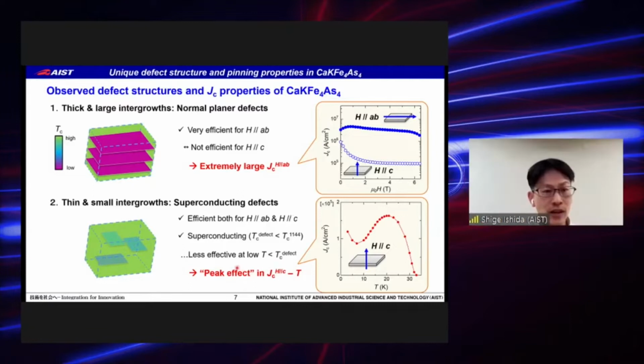So this small thin intergrowth is superconducting at low temperatures. Maybe the defects become less effective as pinning centers. So we expect these kinds of defects are responsible for the peak effect, the increase in JC with increasing temperature observed in this calcium potassium 1144 material.